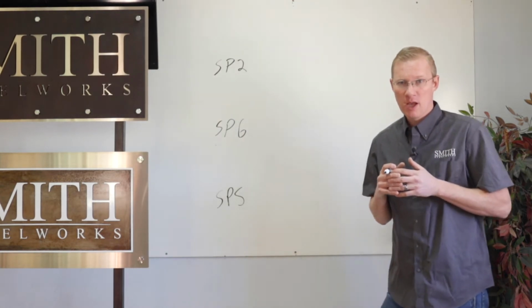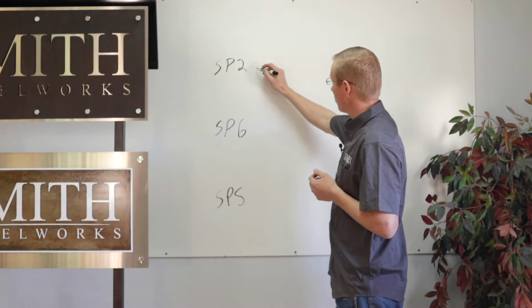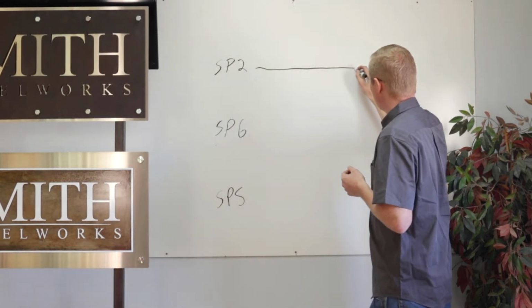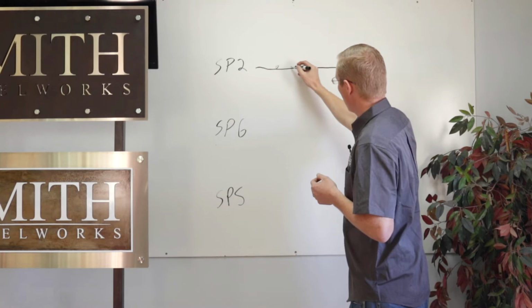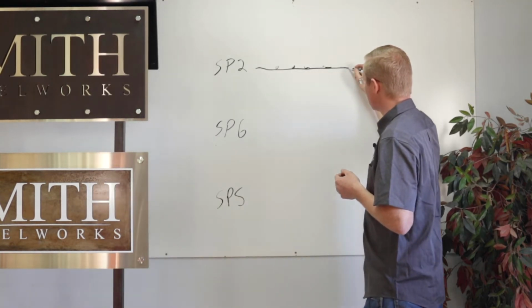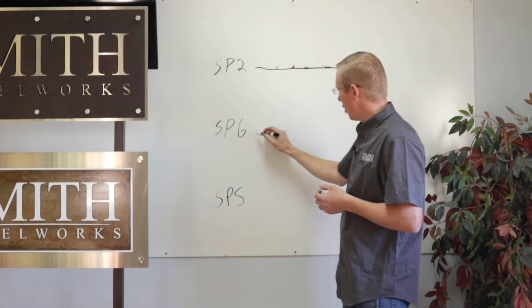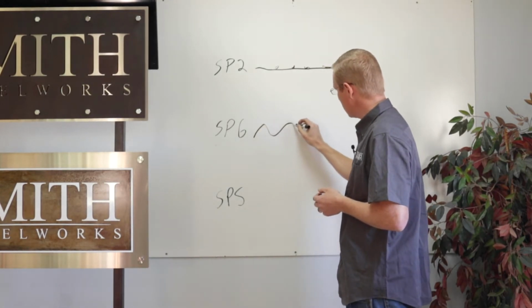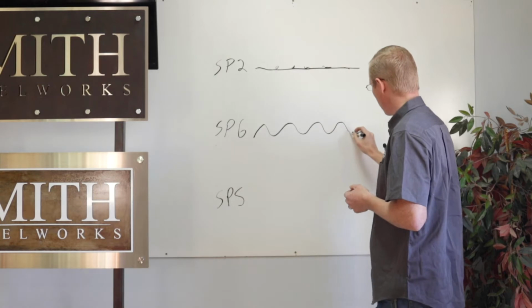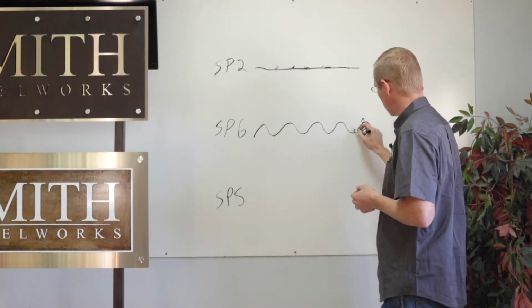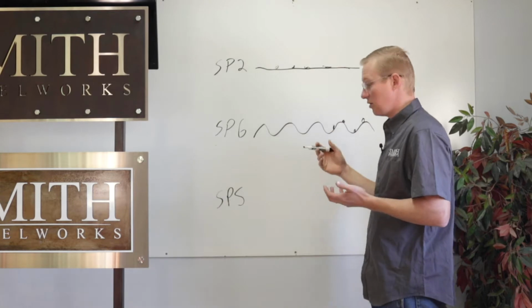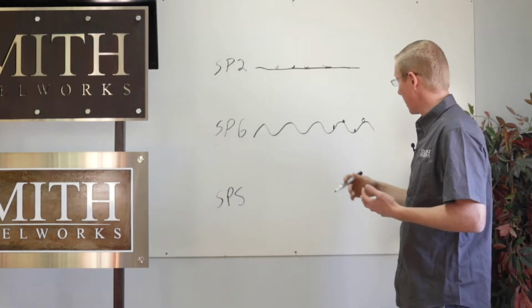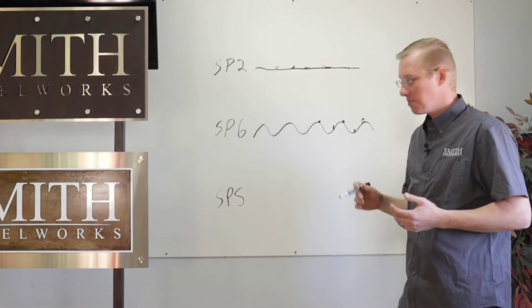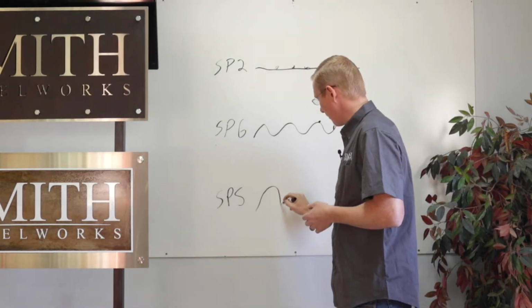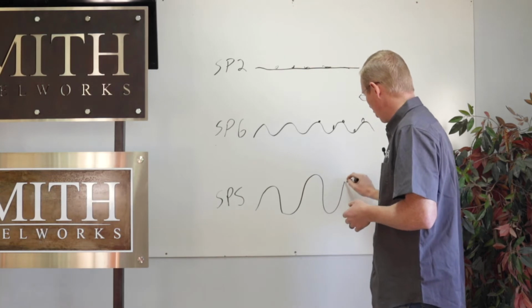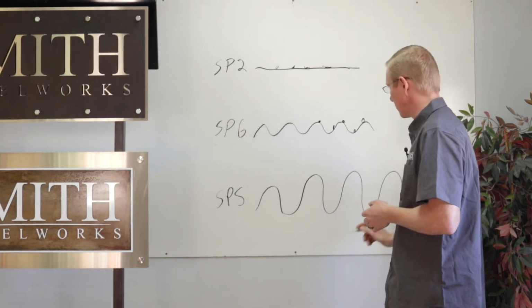protective coating. An SP-2, if viewed under a microscope, would show a relatively flat surface with foreign contaminants throughout the surface. An SP-6 would show shallow ridges and valleys with 33% foreign contaminants left on the surface, meaning your rust, your corrosion, your mill scale, it would all be left on it. An SP-5 would show deeper ridges and valleys with no foreign contaminants on the surface.